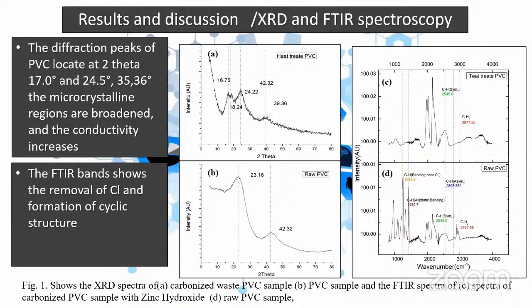Also in FTIR, near 1243, we can see in the figure 1D graph, raw PVC had a Cl bending bond, and after heat treatment, the Cl is removed as HCl and generates the cyclic structure, which is conductive. We cannot see the Cl bond in the treated PVC sample.